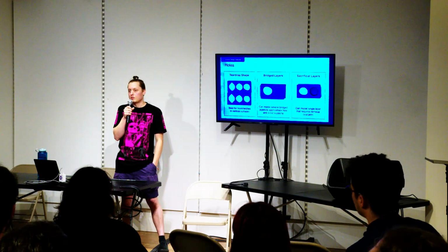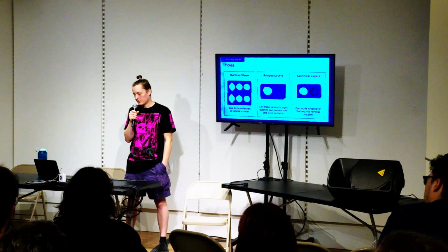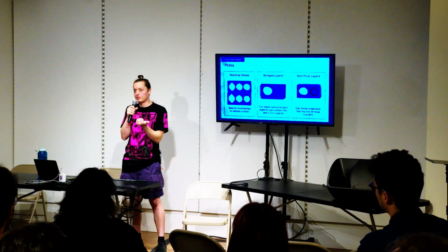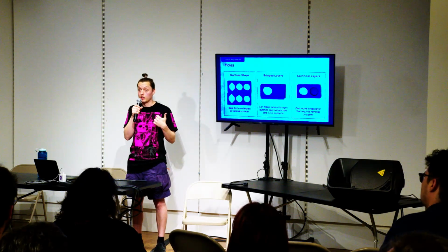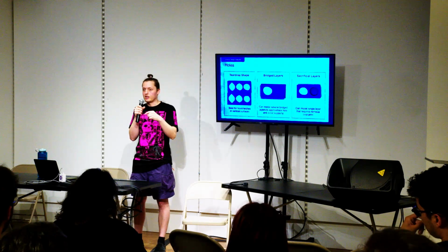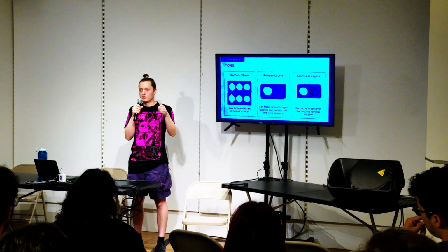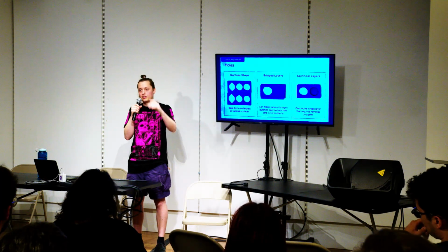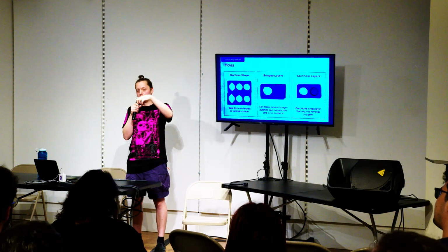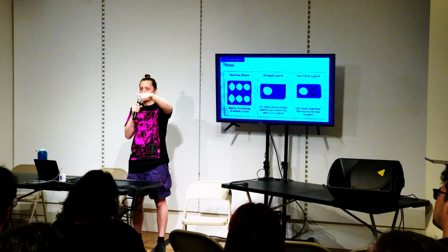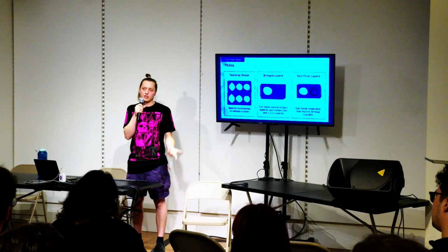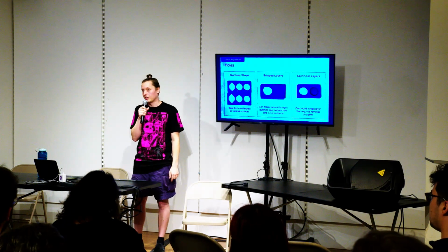Just a little bit. I've found that there's a couple different techniques. Materials like TPU bond across layers really, really well, and usually are watertight. Increasing perimeters can help with making something more watertight because there's less chances of gaps between the layers. Increasing flow rate, maybe even over extruding a little bit so that the plastic gets extra squished as it's getting put down, can help with water tightness. And then you can also finish with an epoxy or some kind of resin coating on an object.